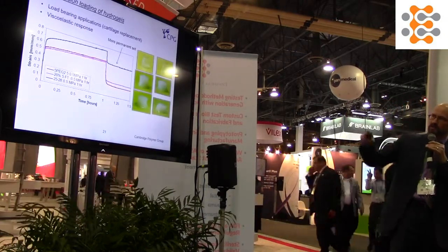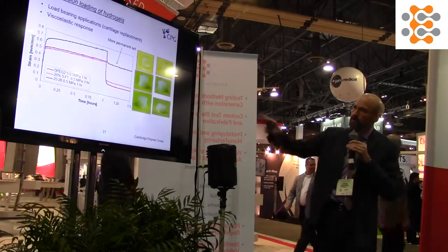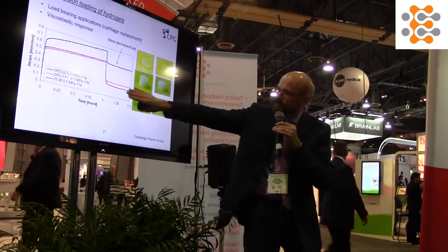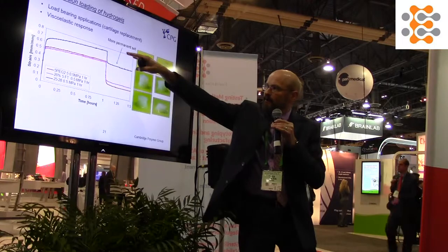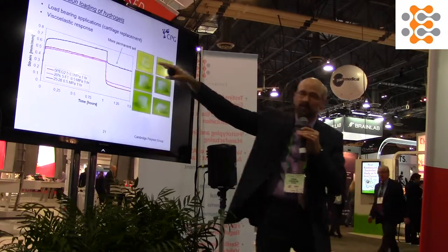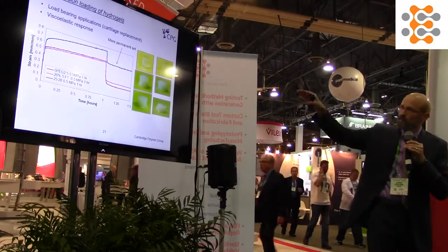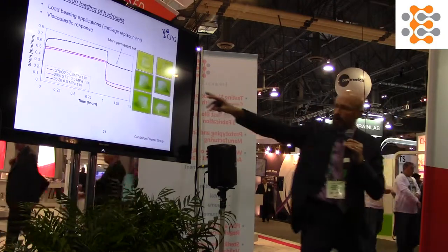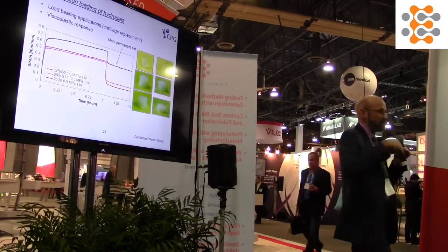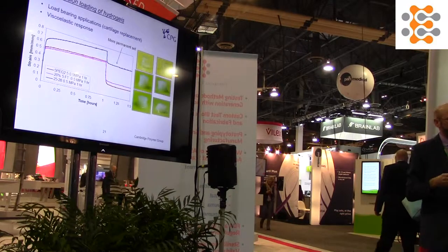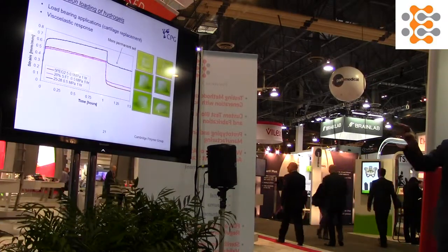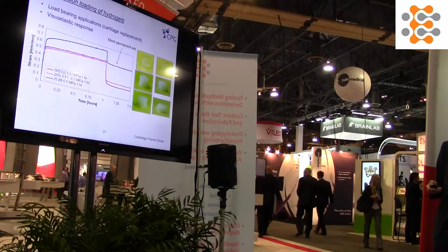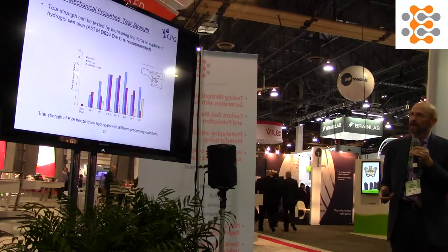Actually, this shows a little bit better here. When a load is applied to a cartilage replacement, we want to see a rapid rise in strain and then a much slower plateau attainment. Once the load is released, we'd like to have this go all the way back down to zero. In other words, full creep recovery, otherwise we're going to be getting shorter and shorter as the day goes on. We're not quite there yet, obviously, but we're making good strides in that direction.